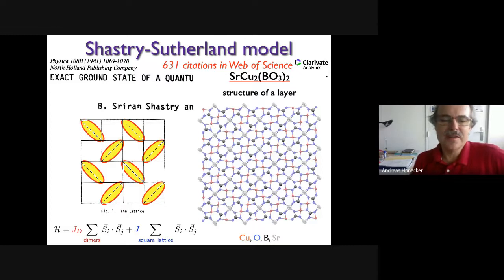Now, the point why this attracted so much attention is that there's actually a realization of that lattice in a material, strontium copper borate. The magnetic ions here are copper ions, and the coppers are red. And you see that there are always pairs of coppers that form a dimer. And if you stare a while at it, you might see that the geometry is exactly the same as you have on the left-hand side in the sketch. So strontium copper borate is in fact realizing that model.